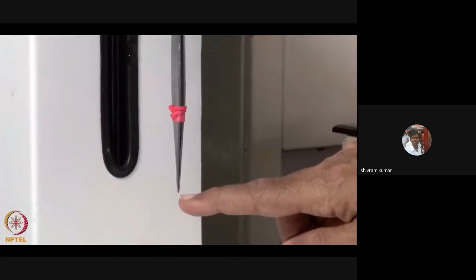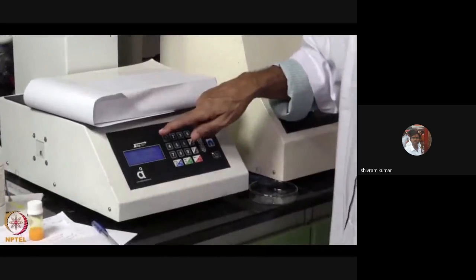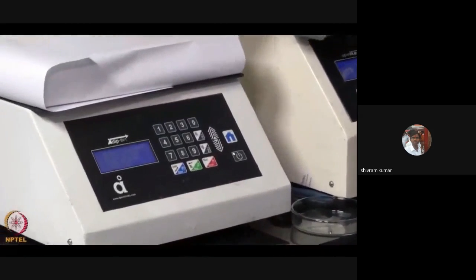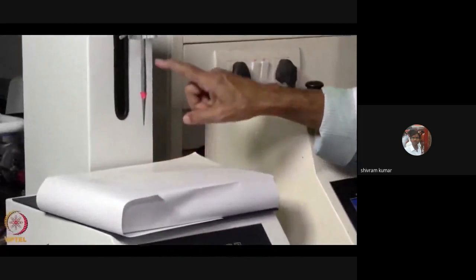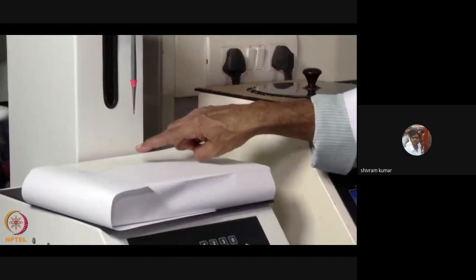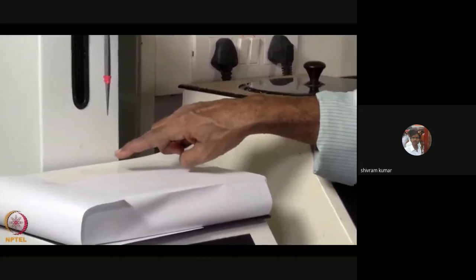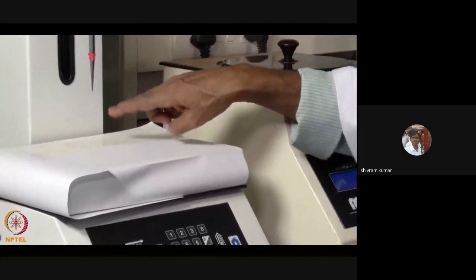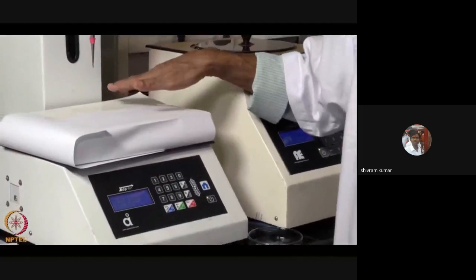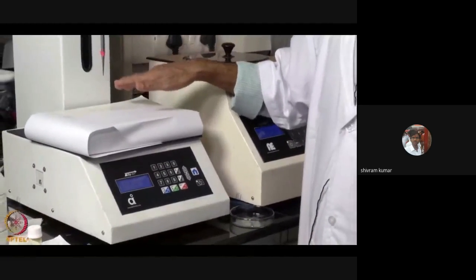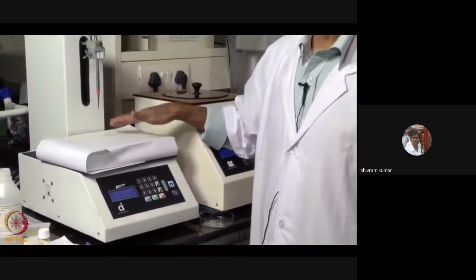We place the polymer film here and we set the program here, and the solution is placed here. The polymer film goes down, dips into the solution, and the coating is achieved. We can dip it several times. We can dip it once, twice, many times depending upon the thickness of the coating design.